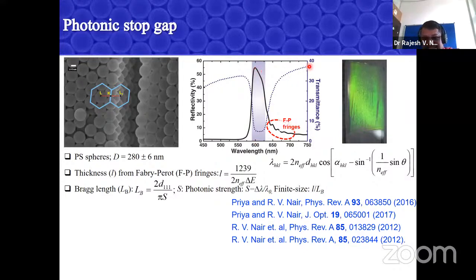And now you see that if I look at the long wavelength, which is at 750, both transmission and reflection do not add up to 100. That means there's a huge scattering in the samples, and that scattering happens because of these kinds of defects, disorder, everything put under one umbrella. And this was one of the challenges in the field of experimental nanophotonics, how to avoid these defects. And later I'll show you when defects are also a good thing to have, because it is the defect which makes people also interested. Okay, so we estimate all these nice parameters, and it all agrees with theory.